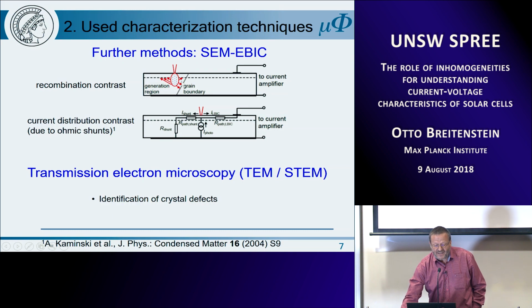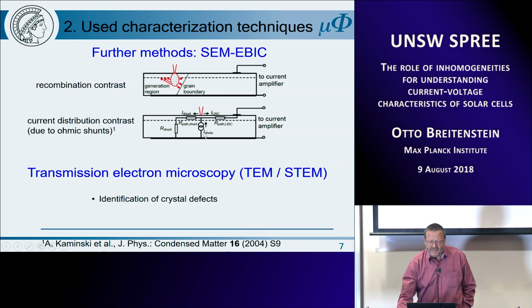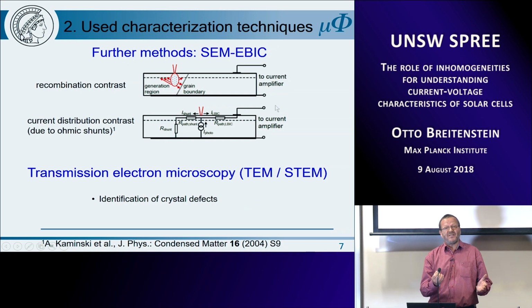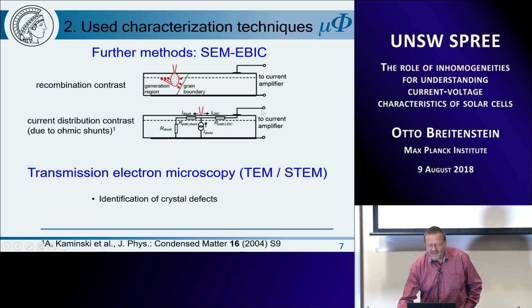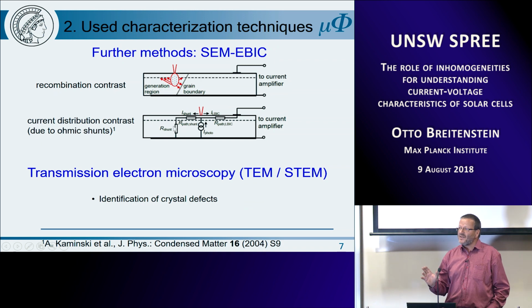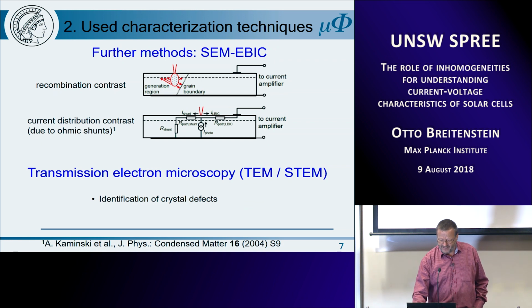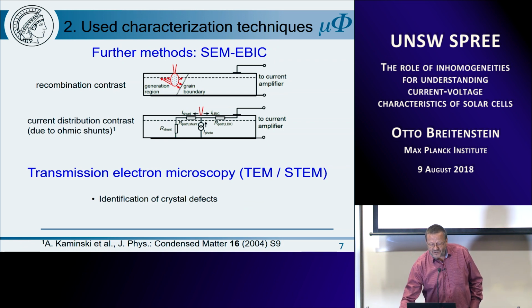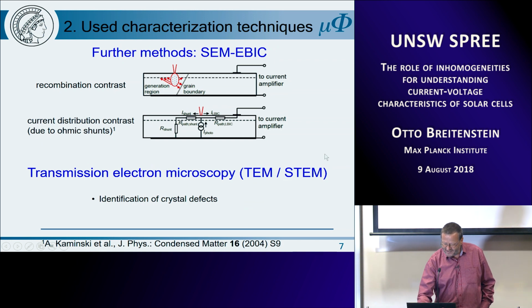But if we have ohmic shunts, we have a current distribution contrast, which we have explained already in 2004. This means if our beam is here, the current can choose to flow to the shunt or to flow to the current amplifier, which also represents a short circuit on its input. Depending on the position, the detected current becomes lower if we come closer to the shunt. That has nothing to do with recombination. It's a current distribution contrast. And then we have used transmission electron microscopy and scanning transmission electron microscopy for identification of crystal defects, as you will see later on.